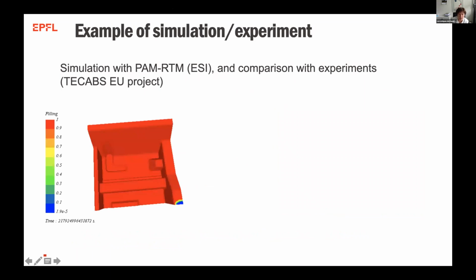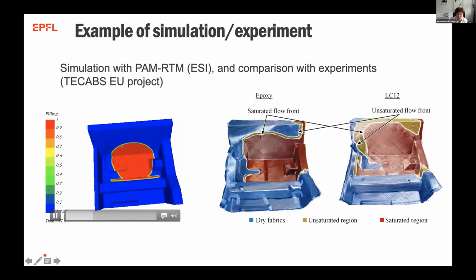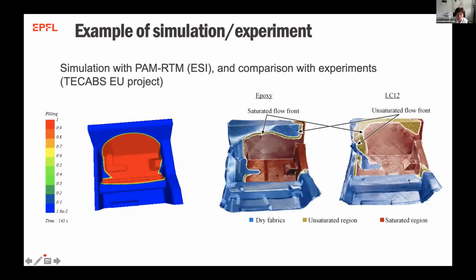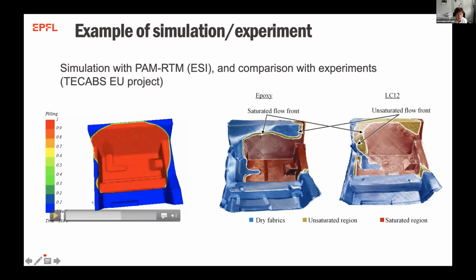What's interesting with all these things is to be able to compare, at the end, if you want to make a part, this is an old example from TechAbs, what you predict during impregnation and what you have at the end. You see here, I stopped it, you predict something that looks fairly uniform, but in fact, when you do a real scale experiment and you stop it, you see that, more or less, it did what you want, but in fact, here it went much faster. In the blue part, which is the dry fabric, you see that it was really compressed, and that was not taken into account in the model. Clearly, we had the same volume fraction everywhere, which is wrong, so you need to change the volume fraction here, and so on.